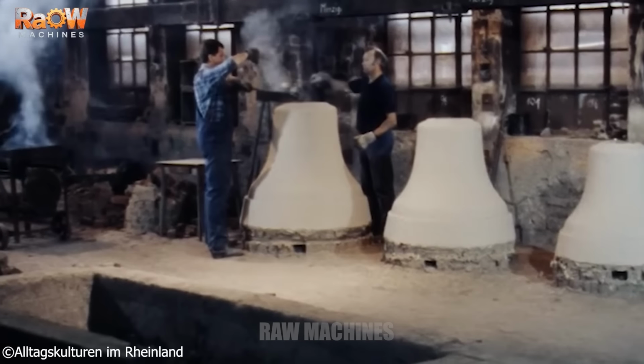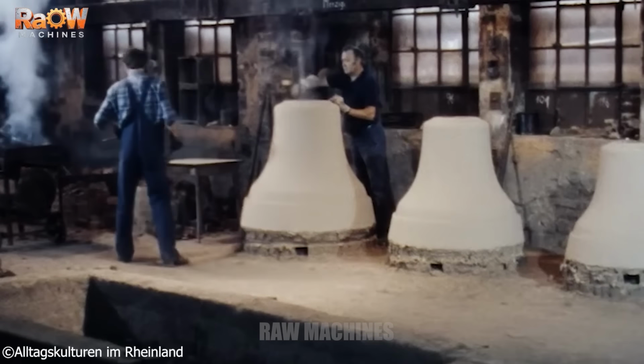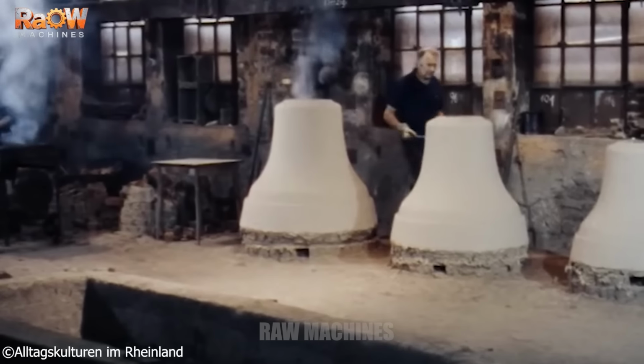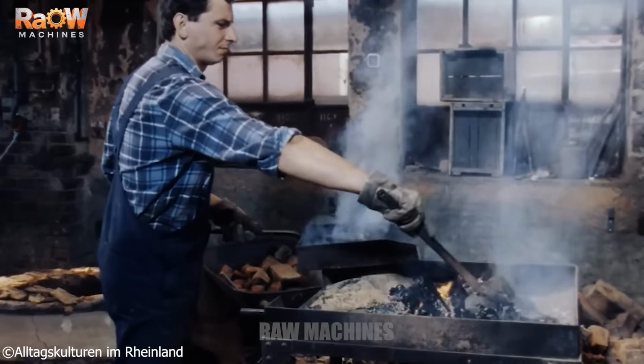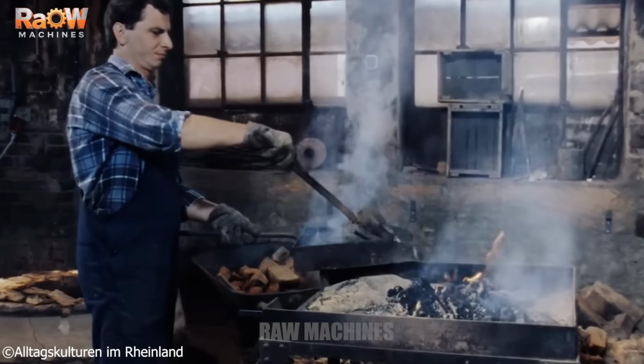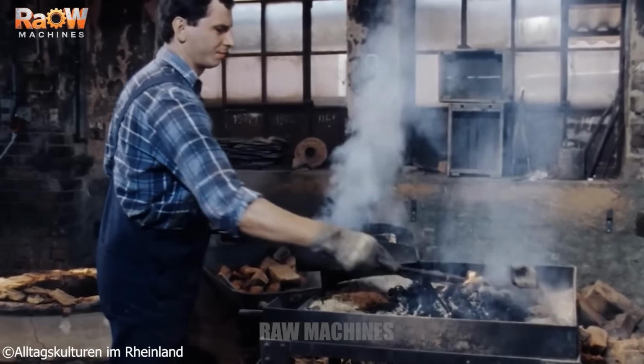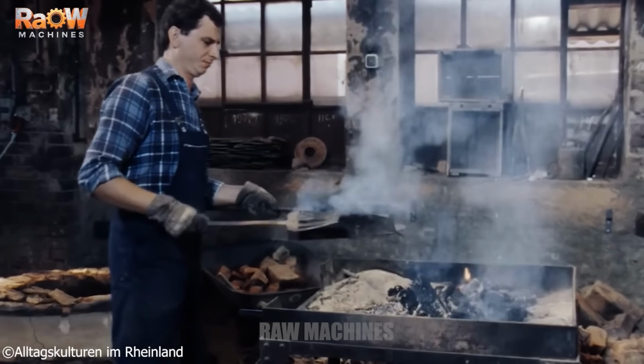During this phase, no fire is lit inside the core, as heat would immediately melt the wax elements. Each layer is applied only after the previous one has fully dried. Up to 12 fine layers may be required to achieve a clean and sharply defined negative surface.